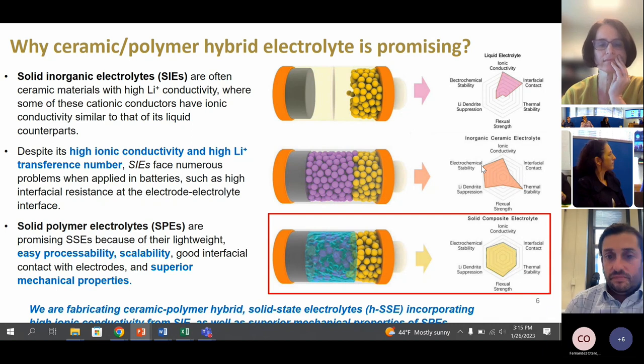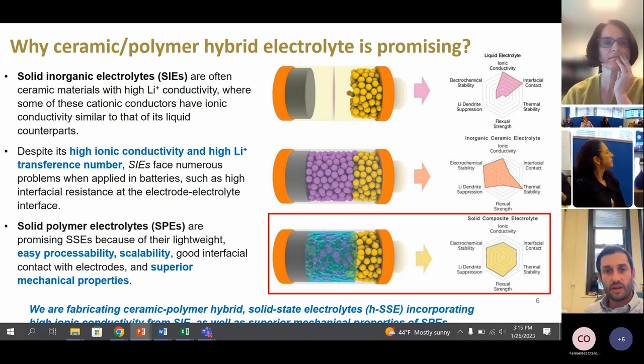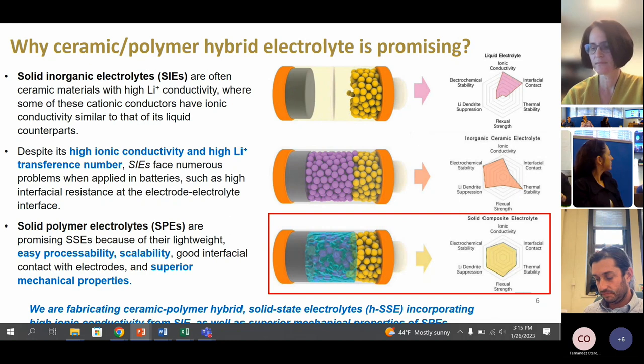So if you think about that, if you take a cup and you fill it up with M&Ms, the bottom of that cup has little holes, areas that are not in contact. And for ionic conductivity, it's that contact, the interfacial contact between those points, which is critical to how these batteries perform. If you take a glass of water and you pour it in, you've got full contact throughout.